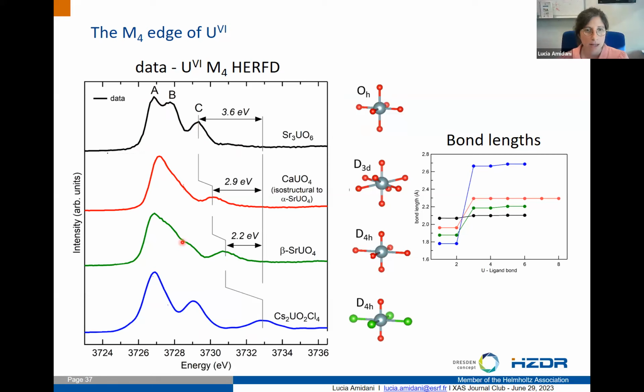In the intermediate cases, we cannot specifically recognize the middle peaks, but we clearly see the lower energy peak moving from this energy to higher energies with the increase of, let's say, shortening of bond distances.